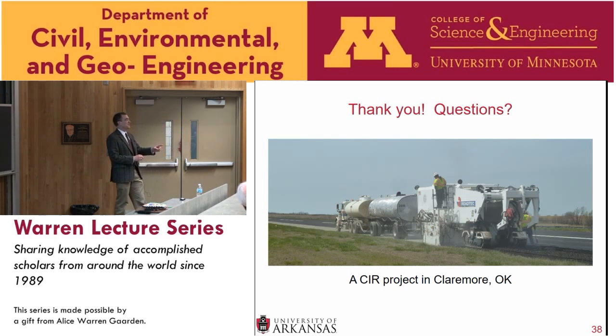Okay, so I'll take the first question first, and I might forget the second question before I finish answering the first one. But the first one is, we noticed a difference between the field limestone RAP and the lab-produced limestone RAP. And what we did is we actually took virgin limestone and we coated it with asphalt emulsion and crushed it. But then we also took crushed limestone and coated it, and we blended those. And it was a 75-25% blend. And we matched it by a grayscale analysis. So we took the field RAP and we ran a grayscale analysis on that. And then we blended the pre-crushed limestone with the post-crushed limestone, because there's some open faces on the RAP. So we blended those together and we matched the grayscale analysis.